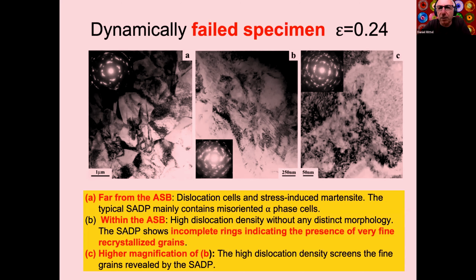Am I telling you something new? Well, I'm sorry to disappoint you. No, this is not new. This is very well known that inside the shear band, the microstructure has evolved and grains have recrystallized dynamically. That's the term, dynamic recrystallization. And you now have nanograins of a few tens of nanometers in size. Whereas at the beginning, we were talking about tens of microns. Now it's tens of nanometers inside the shear band.